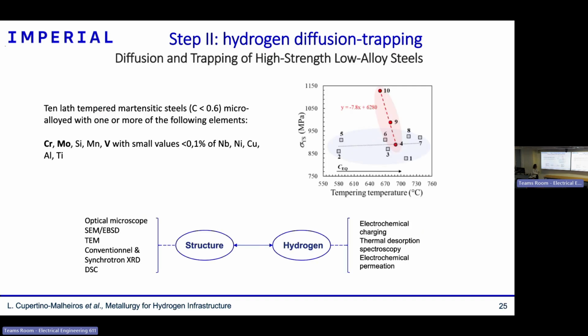One of the pieces of research I have done related to diffusion and trapping considers high strength, low alloy steel. As I said, high strength steels can be very susceptible to hydrogen embrittlement. In this research, I was comparing 10 grades of steels. These high strength steels have a structure called tempered martensitic structure. In this graph you can see the strength of those alloys on the y-axis, and on the x-axis the tempering temperature,